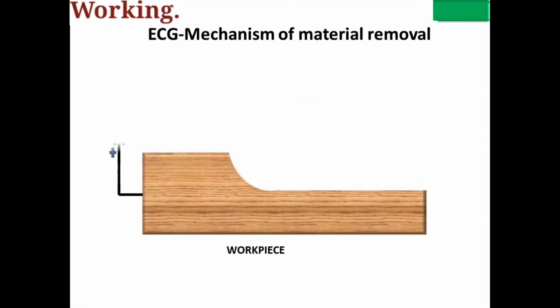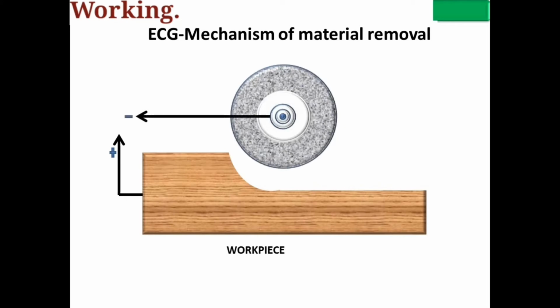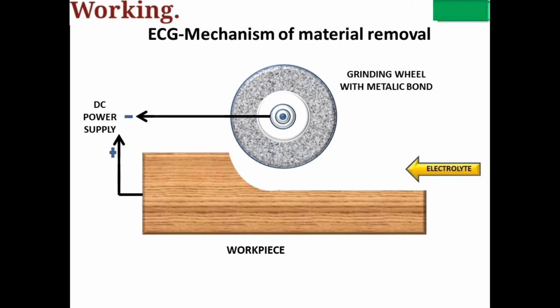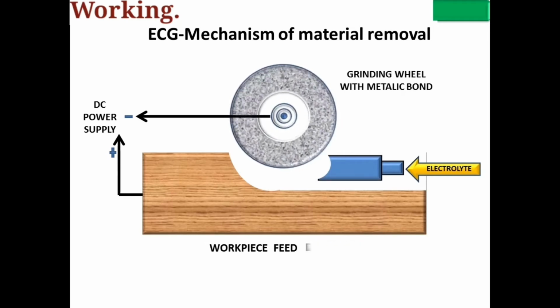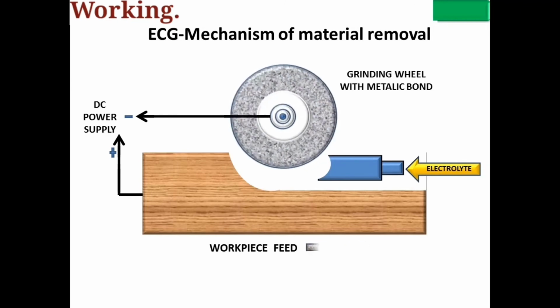Next is the working process. Here the workpiece and the wheel are separated by an electrolyte fluid. The workpiece is connected to the positive terminal and the tool, that is the grinding wheel, is connected to the negative terminal. Also, diamond or aluminum oxide particles are embedded on the grinding wheel as insulating abrasive material and set with a conductive bond material. A nozzle similar to the one which carries coolant in a conventional grinding process is provided to enable the flow of electrolyte fluid to the work-tool contact area. A constant inter-electrode gap of 0.025 mm or less is maintained considering the grain size of the abrasive particles.